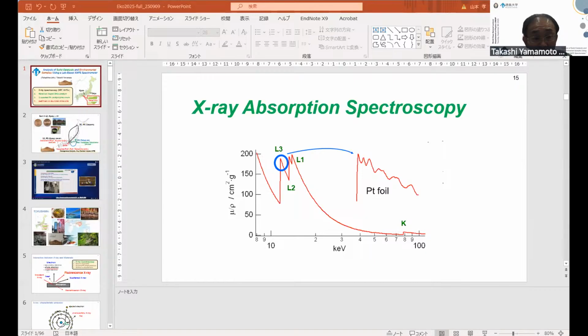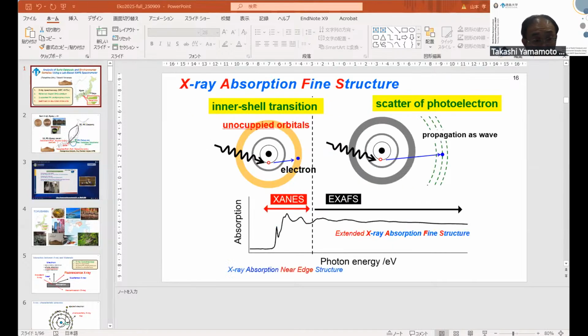chemical and electronic information. This is a schematic of the spectrum. XAFS means X-ray absorption fine structure. Near the absorption edge, up to around 50 electron volts, it is called XANES, X-ray absorption near edge structure. In this region, electron transition to the unoccupied orbitals occurs. So this region contains information about the electronic structures and orbitals.